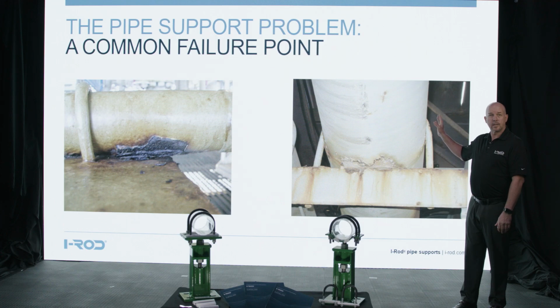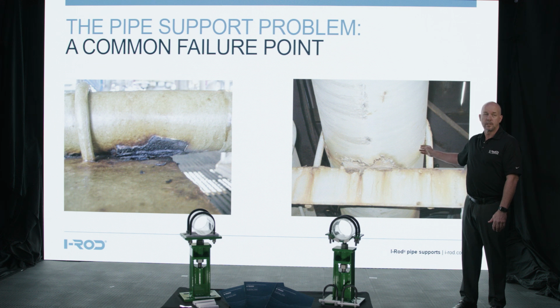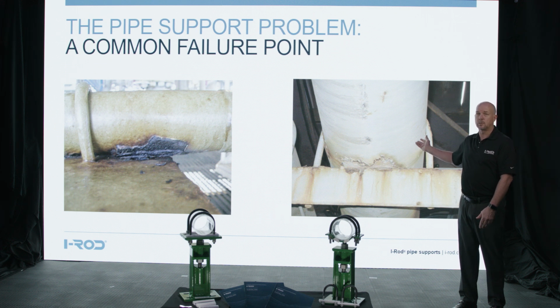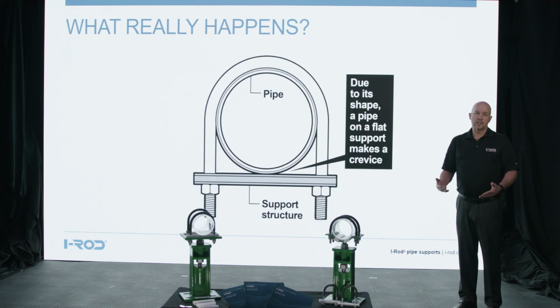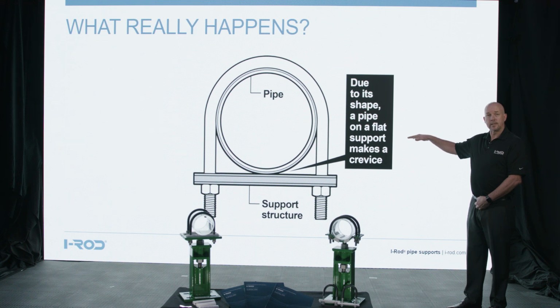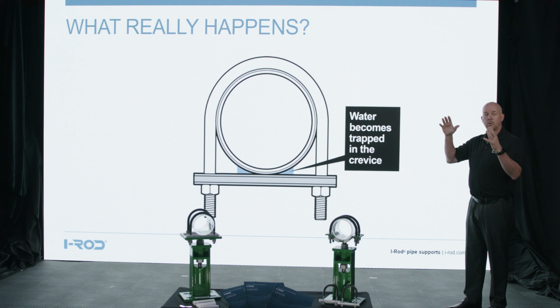You can see there's no damage to the coating that's not in contact with the support, but where the pipe is in contact with the support, you can see the coating is damaged and you start to see some corrosion happening. So there's some misconceptions about how this corrosion happens, but right here we're going to talk about how this really happens. The round pipe sitting on a flat support creates a crevice at the bottom of the support. Condensation or rain, water collects on the outside of the pipe, and then gravity pulls that water down to the bottom of the pipe, and the water gets trapped at the crevice.